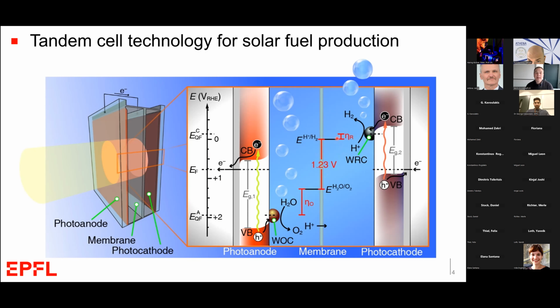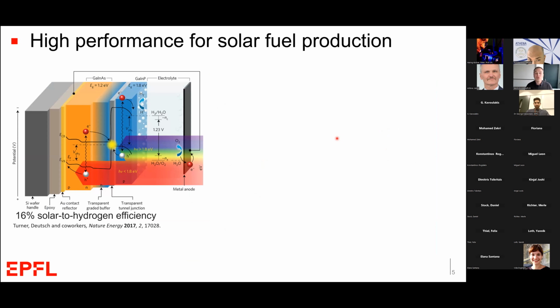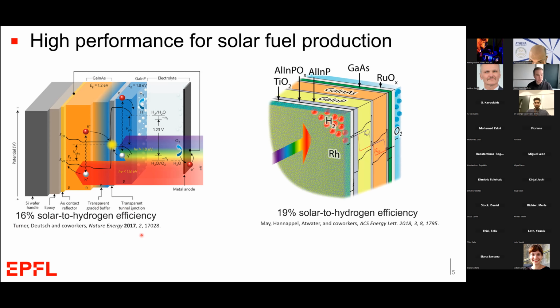Well, high efficiency has been demonstrated by a number of groups. Here are a few examples, one from NREL in the United States, where they show this monolithic gallium indium arsenide, gallium indium phosphide type of photocathode, which develops sufficient photopotential to split water and achieves 16% solar to hydrogen conversion efficiency. That was in 2017, and a year later, Caltech and others produced a similar type of device with some modified layers and achieved 19% solar to hydrogen conversion efficiency.